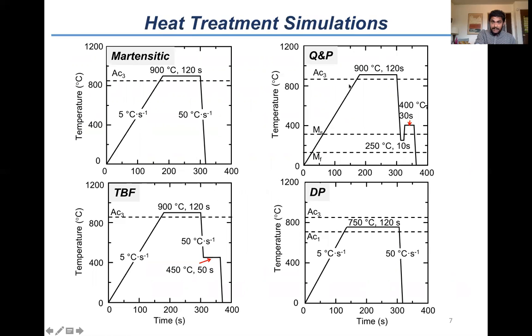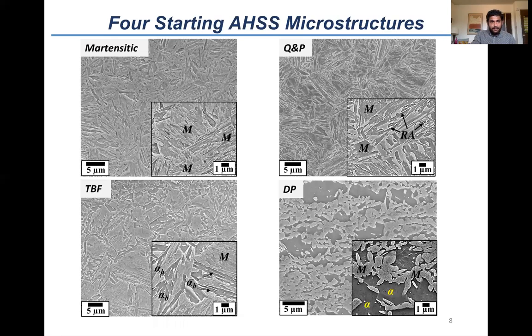Please note that the martensitic, QNP and TBF steels were completely austenitized before the martensite, QNP or TBF microstructures were produced. In contrast, the DP steel was generated through intercritical annealing. So that's an important thing that we have to keep in mind. We'll be coming back to it later on. Here are the 4 different microstructures corresponding to the cycles that I showed in the previous slide. This is the martensitic microstructure, the quench and partition microstructure, which is martensite and retained austenite, the TBF microstructure, which has martensite and bainite, and the dual phase microstructure, which is ferrite and martensite.